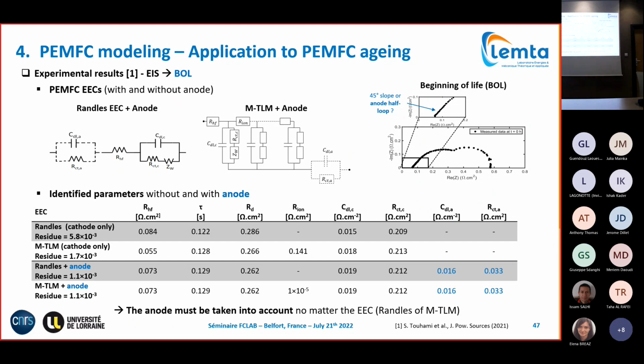And if we additionally connect the anode circuit, we obtain identical values for all parameters in common. A very low ion resistance means that ion conduction in the electrode is negligible, meaning an interfacial electrode, which would be in agreement with the fact that we use commercial very thin electrodes. We also succeeded in identifying identical anode parameters. Therefore, we concluded that the anode must be taken into account. The TLM can be used as well instead of the Randles, but as there's no additional information to get, for simplicity we use the Randles circuit as much as possible.